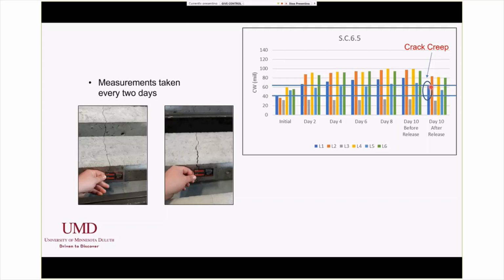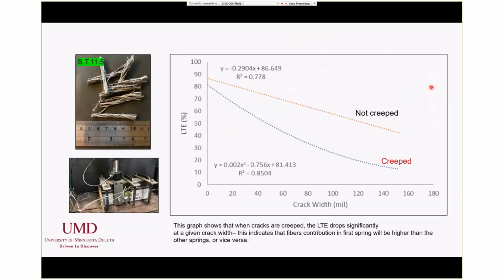If we expand the crack, fiber gets some plastic elongation, or some fibers can pull out. So the plastic elongation of the fiber or the fiber pull out, these two create this crack creep. Now this crack creep influences the load transfer. This is again a very simplified graph. We have scattered data, so my student just plotted a trend line.